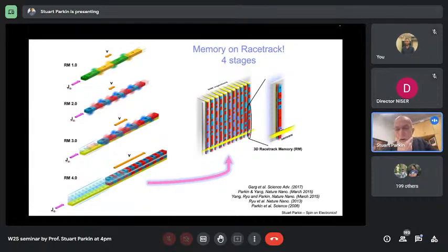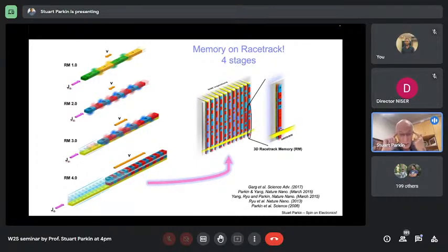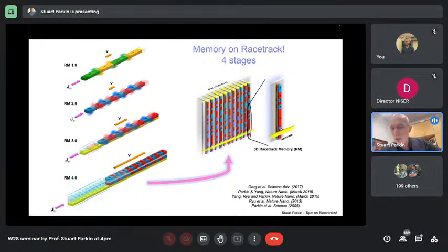However, if you change to materials in which you have significant perpendicular magnetic anisotropy, now the size of the domain wall is governed by the ratio of exchange to this anisotropy. If the anisotropy is big enough, then the domain walls are very narrow. We estimate the domain walls we currently are using in atomically engineered cobalt-nickel multilayers are of the order of 6 nanometers in width. And these domain walls, if we pass current through a cobalt-nickel multilayer, will also move with current. And as you can see here, they move in the opposite direction to the current. That's because the polarization of the current in these nickel and cobalt-based alloys is majority spin polarized.